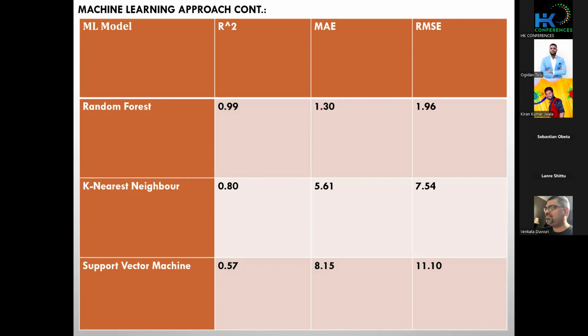As we can see, it was observed that random forest, which is this, demonstrated the best performance, achieving the highest correlation coefficient of 0.99 against 0.8 for k-nearest neighbor and against 0.57 for support vector machine. And also this random forest had the lowest mean absolute error of 1.30 against 5.61 for k-nearest neighbor and against 8.15 for support vector machine.